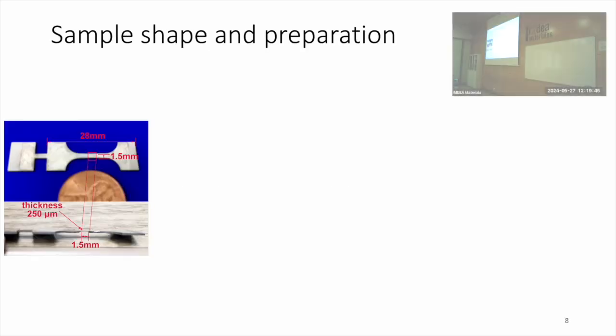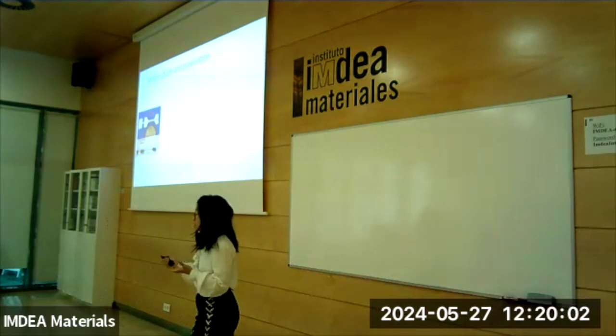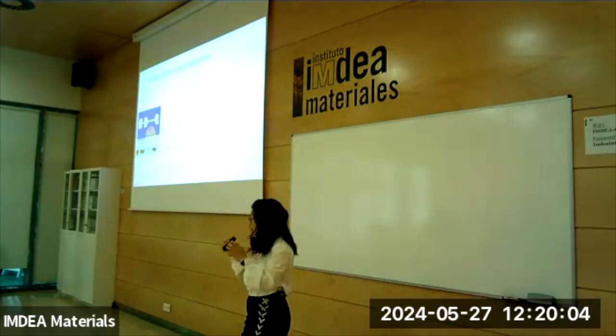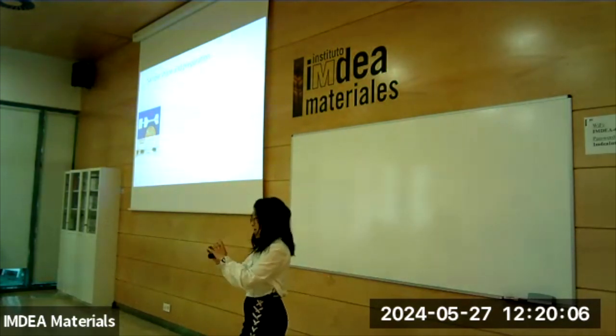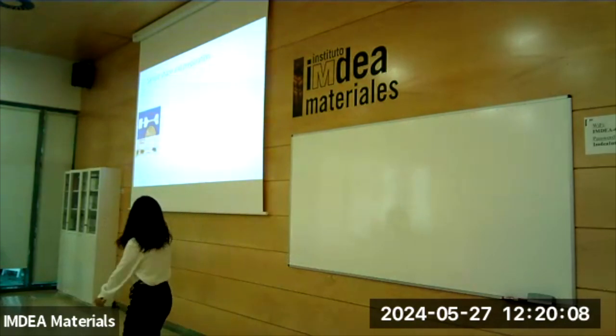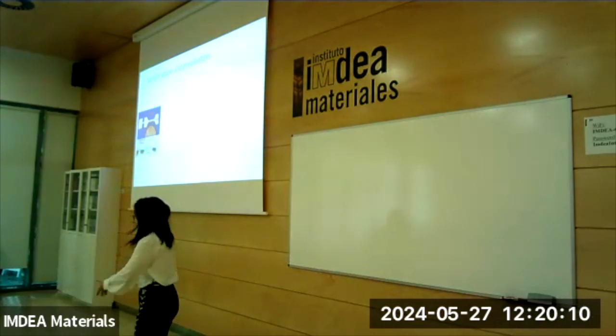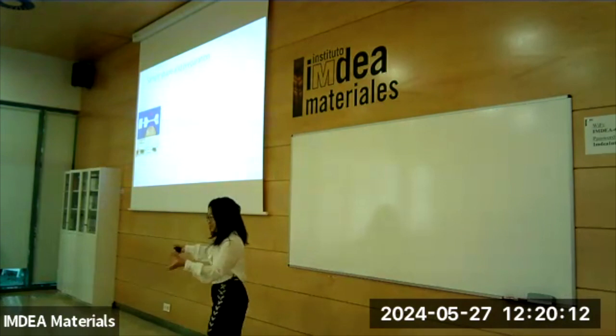So let's take a look at how we prepare our sample. So I got a specimen that looks like this. You see, this is a standard dog bone. And in the middle, we make it extra thin. So when we observe it under the SEM, we only observe a very small area. So now we can make sure the area we observe would have crack. So we don't have to search everywhere.